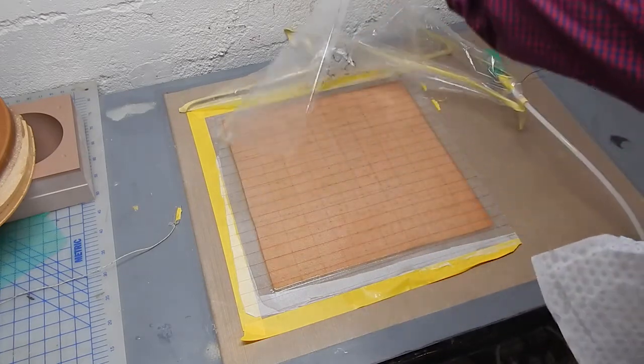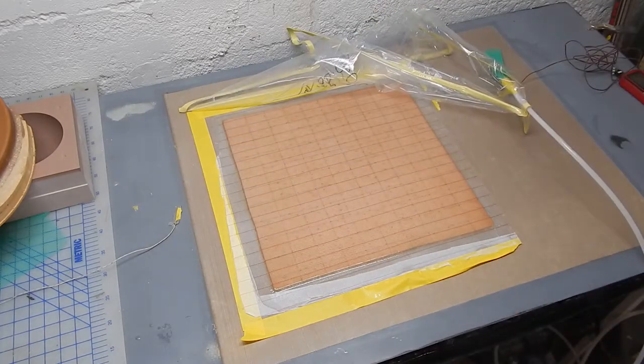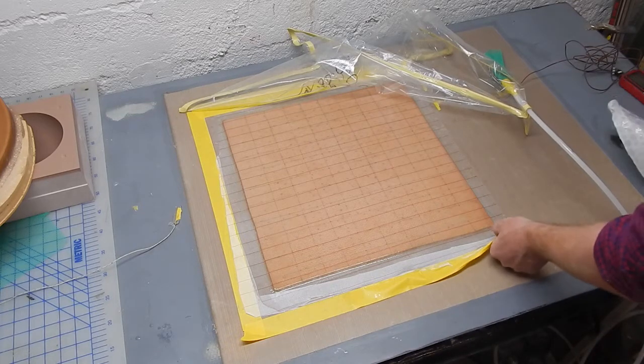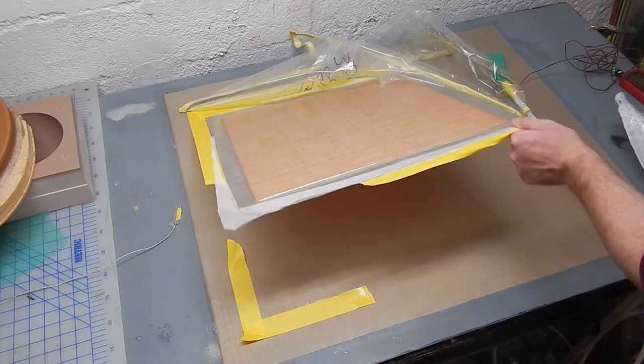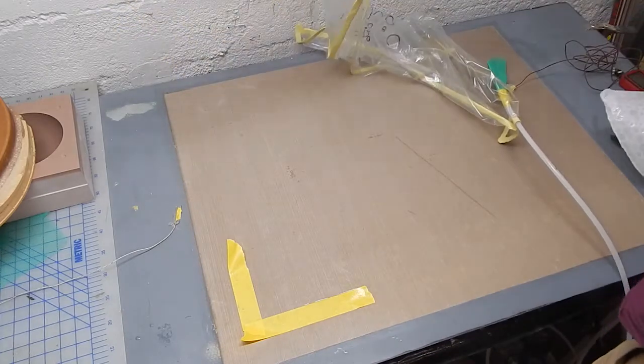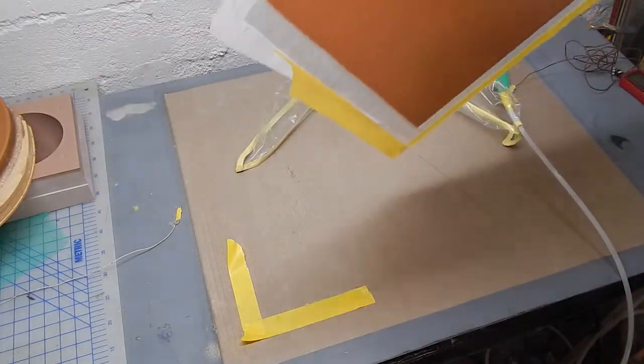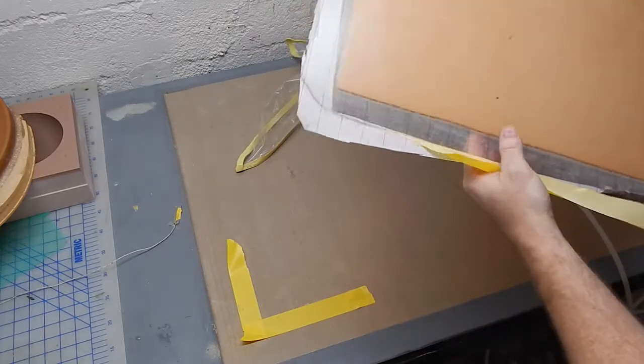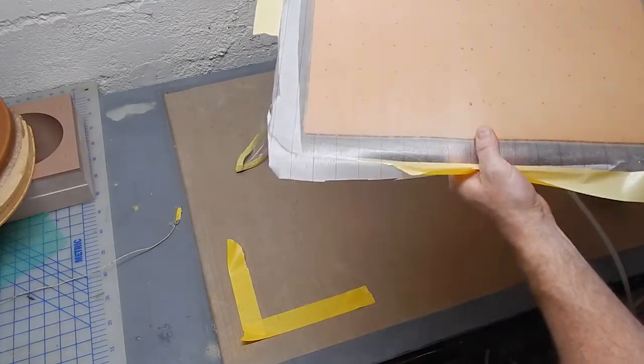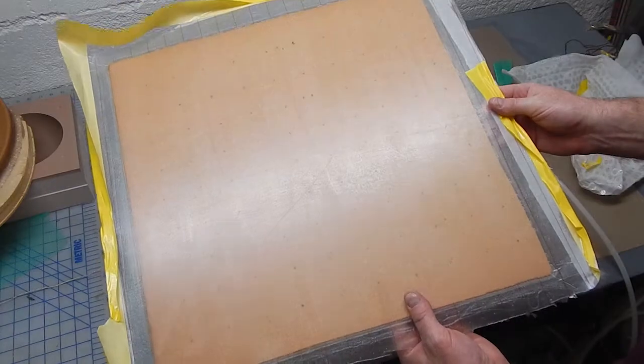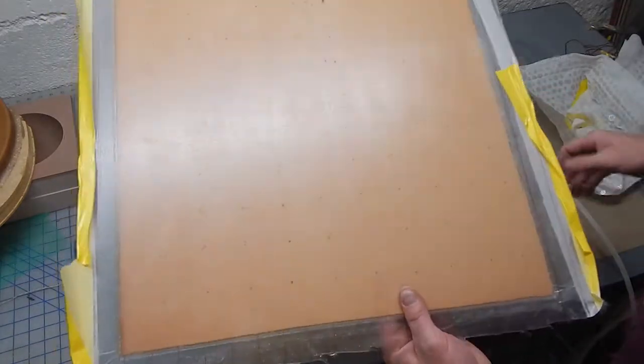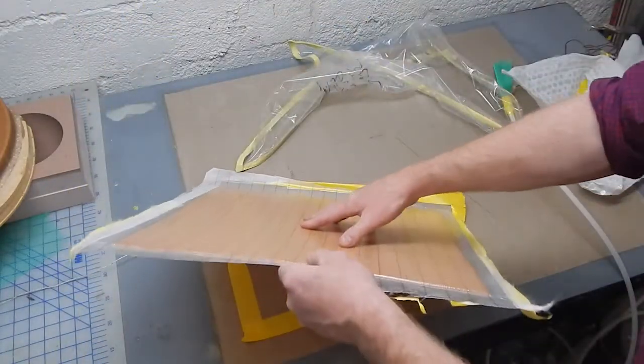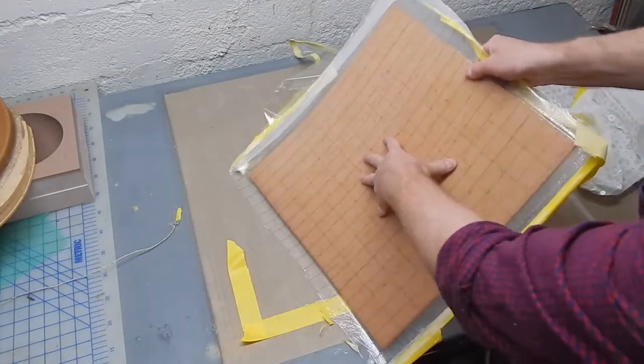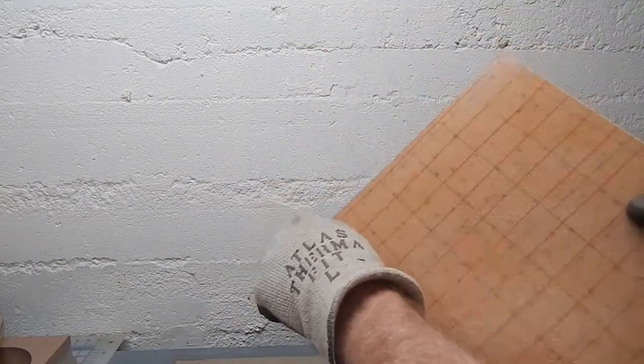There goes the release film. And this pops right off that adhesive Teflon nicely. And just adding that 1/8 inch core makes this an awful lot stiffer than sample number 17, which is just the two plies without any core at all. You can see a rough idea of how bendy it is there. And I trimmed it up to a 1 foot square, and peeling off the peel ply here.